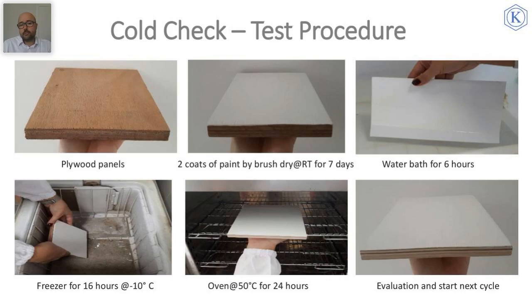And the test starts with a water bath for 6 hours. And after 6 hours, the panels from the water bath are immediately placed into the freezer for 16 hours at minus 10 degrees Celsius. And when the time is over, the panels are then carried to an oven for another 24 hours, which is set to a temperature of 50 degrees Celsius. In total, one cycle is actually 2 days. And after 2 days, careful evaluation is made on the surfaces to follow the cracks.